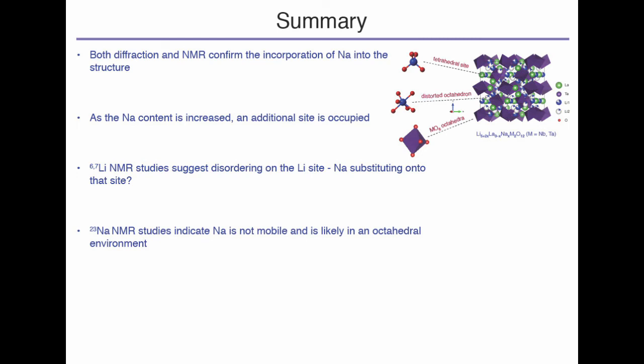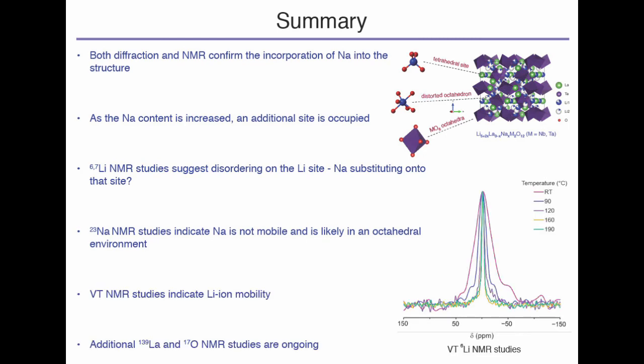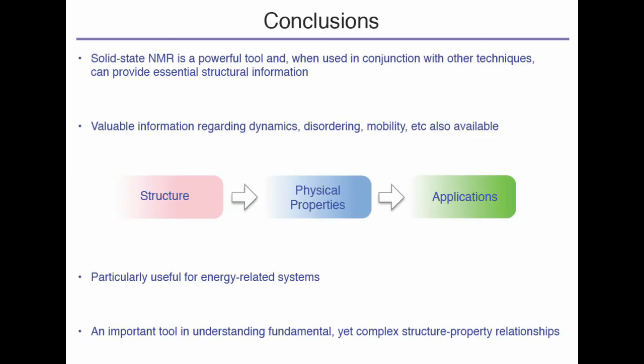Sodium NMR studies indicate that the sodium isn't mobile, so it goes in and it blocks those pores. It doesn't help and contribute to the ionic conductivity. And then, as I said, variable temperature studies indicate the mobility, and additional lanthanum and oxygen studies are still ongoing, but they seem to tell us what's happening locally.